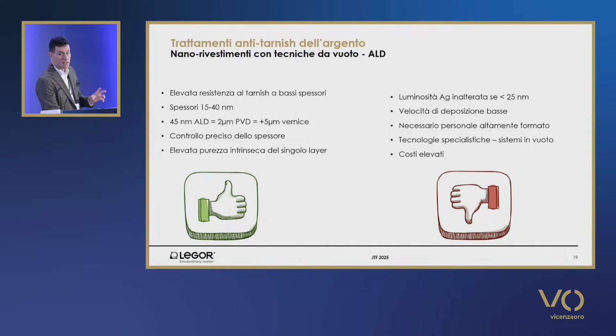So this technology makes it possible to create high resistance barriers with a low thickness, 15 to 40 nanometers, and such a small thickness can be very effective. There are studies which have demonstrated that the same deposit has the same resistance as a similar deposit made by PVD and deposits above 5 micron made with normal polymer-based resins. And this makes it possible to control the thickness and also the compactness of the layer.